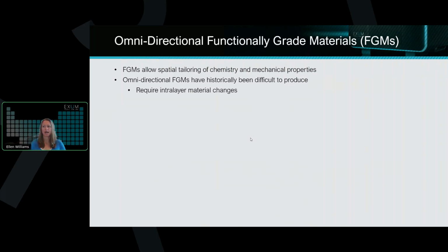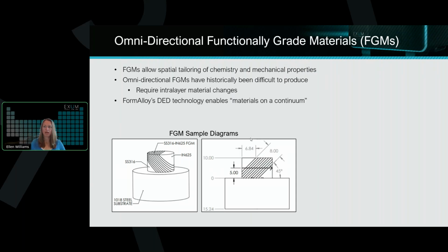They're typically done by directed energy deposit, or DED, and in the past, it's relatively straightforward to change powder types between layers, right? So I'm printing with a stainless steel, now I switch to an Inconel, but omnidirectional functionally graded materials, where we actually change mid-layer, has traditionally been fairly difficult to do because of that intralayer material change. You may be familiar with a company called Formalloy that has developed some pretty innovative technology that allows these omnidirectional functionally graded materials, or as the Department of War calls it, the materials on a continuum.